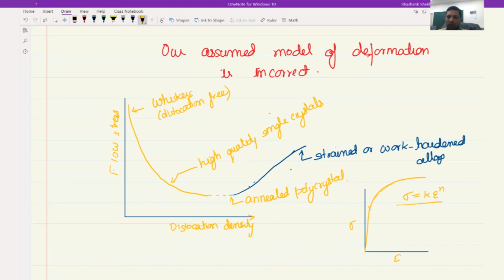And based on that, together they came up with the model of dislocations. And when you have dislocations, in strain hardening, what is happening is that dislocation density is increasing. From an annealed material, which is somewhere over here, to this particular point, dislocation density increases, and here you get a much higher strength. Of course, it is nowhere close to the whiskers, but it is much higher than the annealed material, and that is why most of these sheet metals that are used are in the rolled condition, because in the rolled condition you get higher strength in the material.